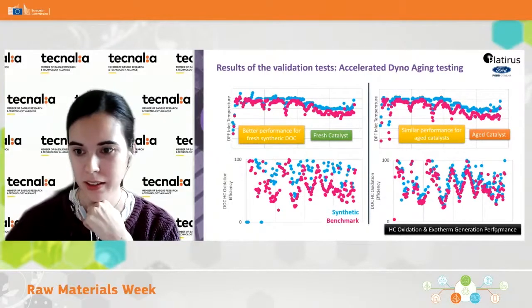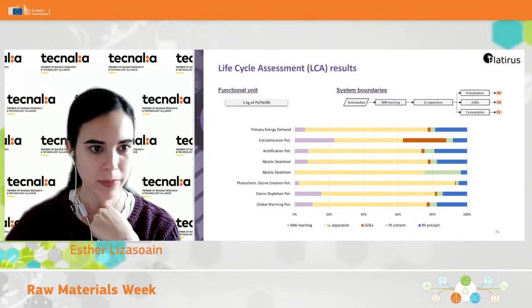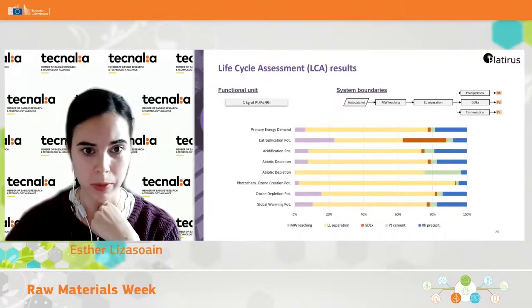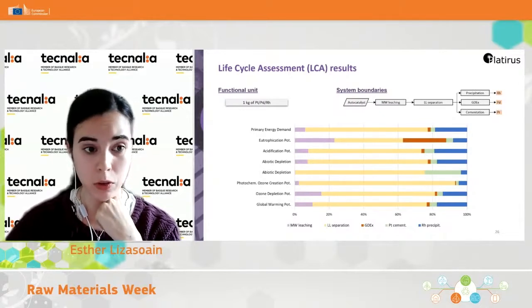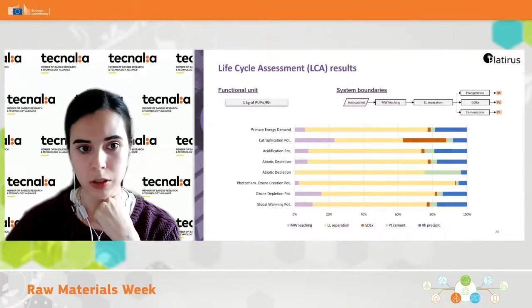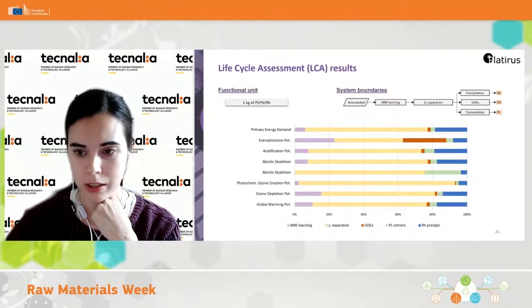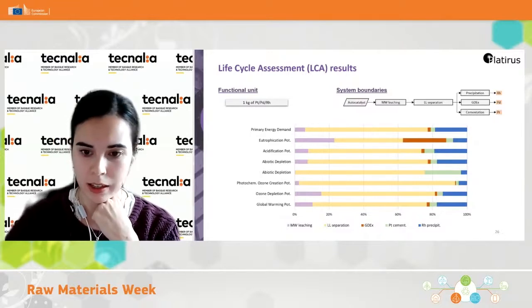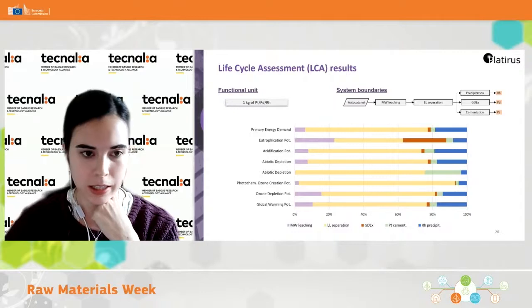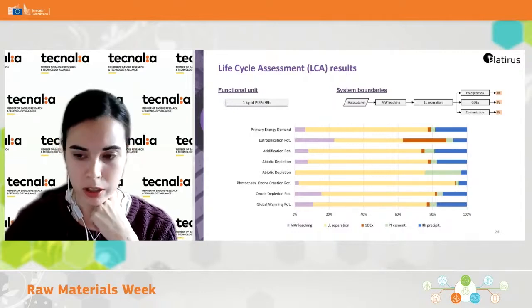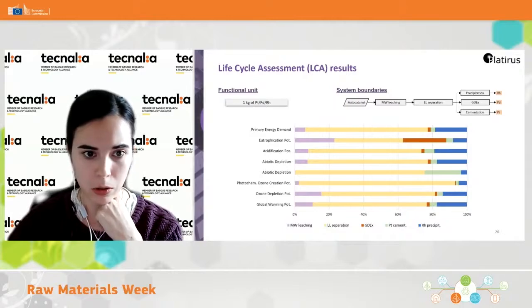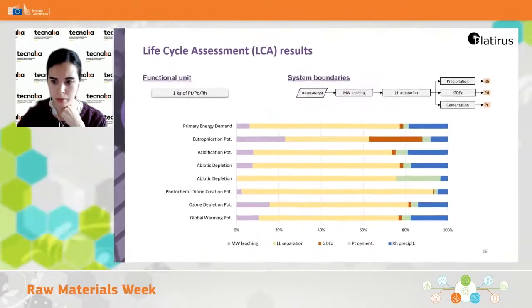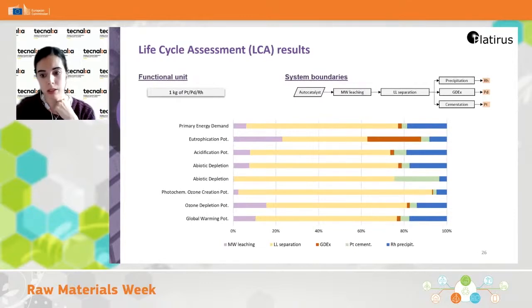Yes, thank you, Joanna. Next slide, please. Okay. Life cycle assessment was performed to determine the environmental impact of the Platirus flowsheet, to identify which are the key contributing parameters, and therefore to support its optimization. And the LCA was performed considering 1 kilogram of PGMs recovered and the 8 impact categories that can be seen here in this slide. Results show that the liquid-liquid separation, that is the process shown in yellow, is the process that is producing most of the impact, reaching the maximum in the photochemical oxidant creation potential and the minimum in the eutrophication potential.